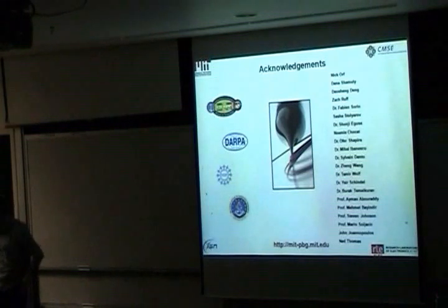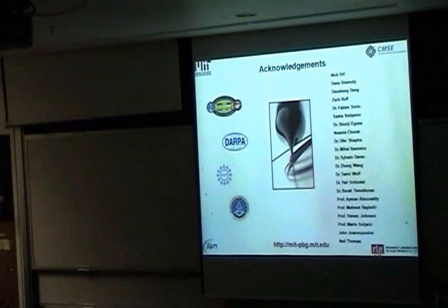Yeah. How long can you draw your fibers out, and what kind of attenuation do you see? I'll give you the place where this has really been explored on a serious level, which is in production runs. A production run today is maybe 500 meters. Now these are fibers with 10 micron features, so they're fairly large. Typically, fibers are used at 1.5 meters, so you don't have to go through the 500 meters, but you need to cut it into sections. Attenuation at 10 microns is on the order of a tenth of a dB per meter. Wow. That's a ballpark.